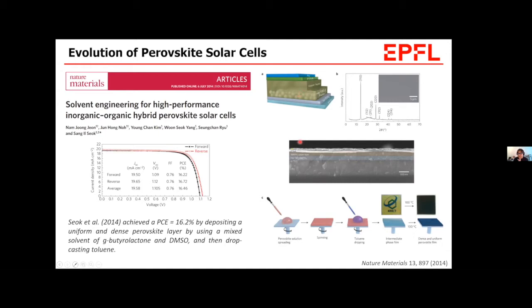In this work, they introduced new technologies for uniform and dense formation of perovskite layers. Before this work, the low vapor pressure of DMF, the typical solvent of the perovskite solution, retards its evaporation, and this leads to slow nucleation and rapid growth of perovskite. It was very hard to reproduce a uniform perovskite film.